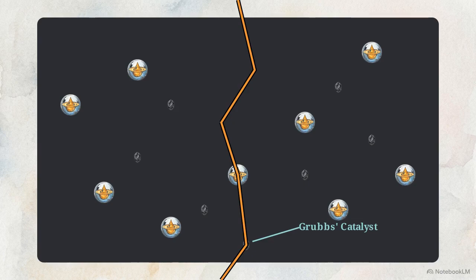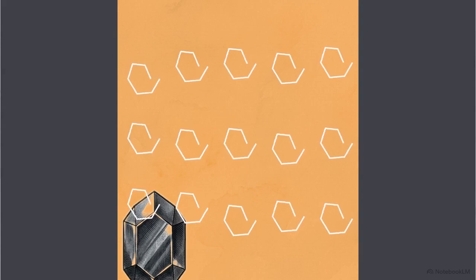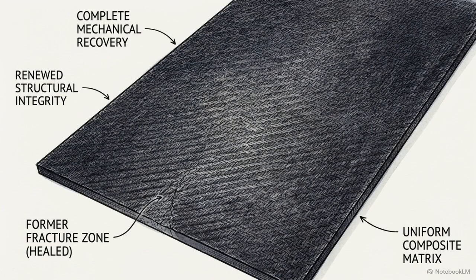Dispersed alongside the capsules in the host matrix is a ruthenium-based Grubbs catalyst. When the flowing DCPD contacts this catalyst, a rapid chemical reaction begins. This triggers a ring-opening metathesis polymerization, or ROMP. The cyclic olefins in the DCPD monomer transform into a dense linear polymer, which permanently cross-links the two fractured surfaces. Because the resulting ROMP polymer is highly durable, this extrinsic method yields exceptional mechanical recovery. It can restore up to 90% of the material's original fracture toughness, making it highly suitable for rigid, load-bearing aerospace composites.